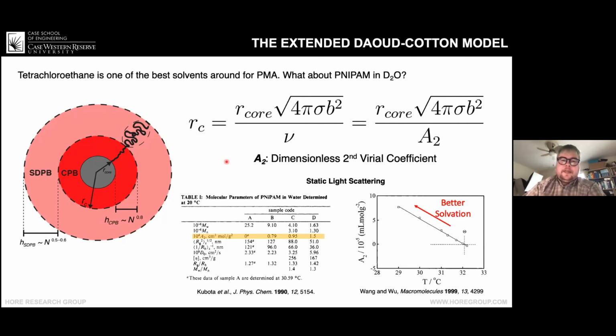Well, that's a great observation, because there is one other study in the literature that looks at NIPAM grafted to spherical particles. They take a different approach to analyzing it, and they don't do the deuteration that we do. But the point is that this parameter obviously controls the transition between those two regions. Their particles were 100 nanometers in radius, so they're much bigger than ours. Ours are about 15 nanometers in radius. In their case, they find that their chains are super highly stretched. So to answer your question, there is some use in doing that.